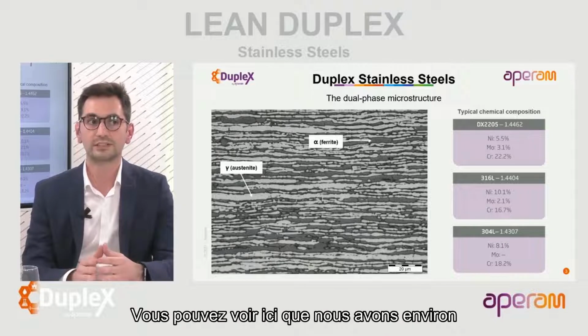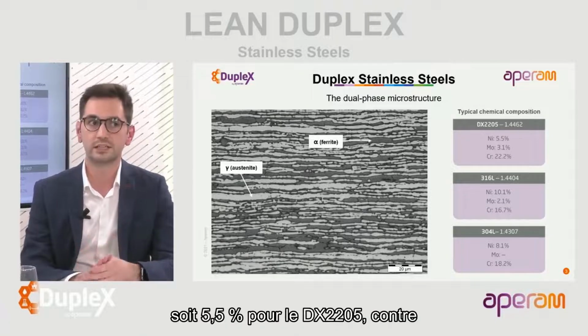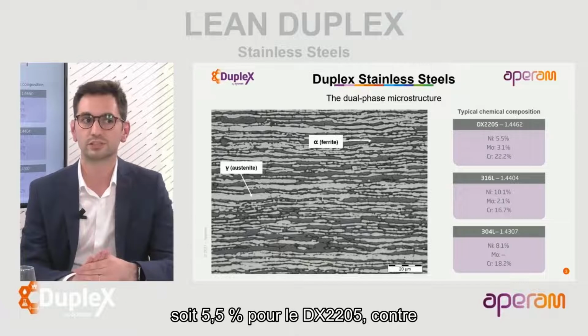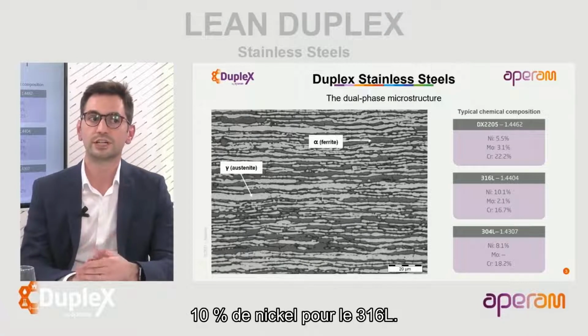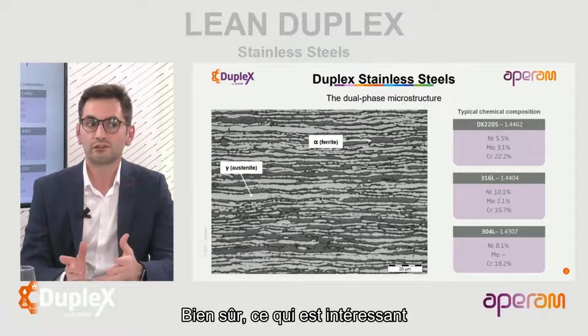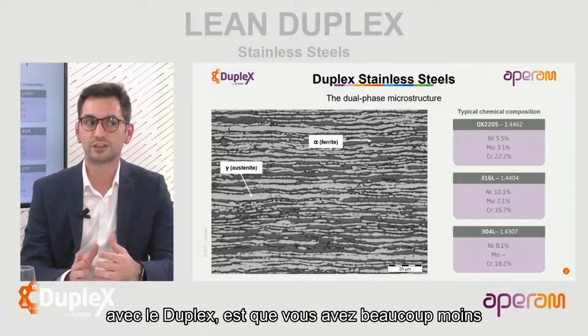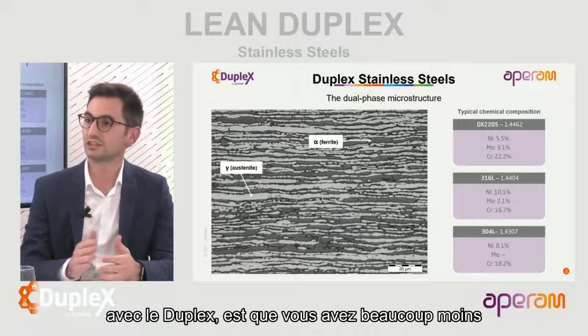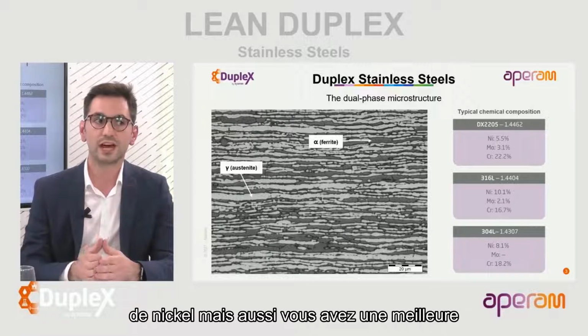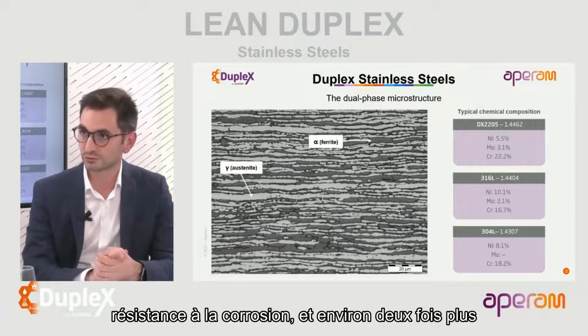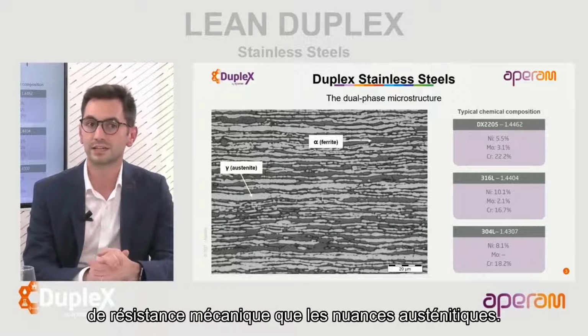So here we can see that we have about half the nickel, 5.5% for the 2205 compared to 10% of nickel for the 316L. And of course, what's very interesting with duplex is that you have much less nickel, but still you have a much higher corrosion resistance and about twice the mechanical strength of the austenitic grades.